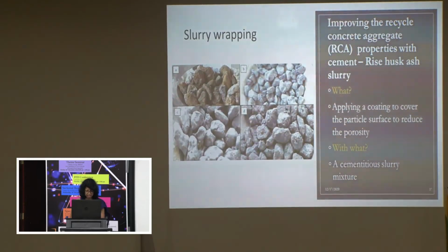Rice husk ash, a good pozzolanic material as well as a commonly found waste material in Sri Lanka, was selected to improve the recycled aggregates in this work. Rice husk ash is a waste produced from the parboiling process of rice. The rice plant absorbs silicon dioxide from the substrate and stores it in the husk of the rice grain. Consequently, rice husk ash has a high percentage of silicon dioxide, which is a good pozzolanic material. It was observed that the incorporation of rice husk ash in concrete can reduce permeability, enhance workability, reduce heat evolution, and obtain large strength gains.